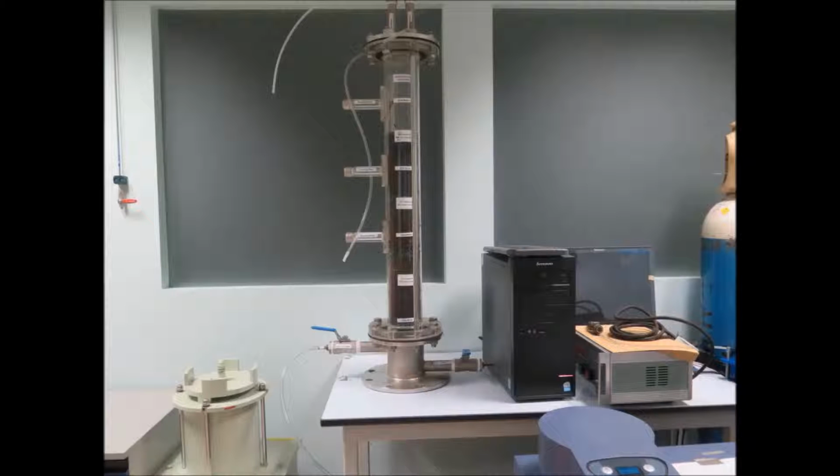So you basically increase the absorptive capacity. Exactly. We do the carbonization, at the same time we create porosity, using a chemical reagent at a particular temperature, and in the end we come up with a highly hydrophobic material with a very high surface area. We're talking about 2,500 square meters per gram, which is far higher than what you get typically from commercial activated carbon. On top of it, it's also hydrophobic and has high porosity. We're talking about microporous materials, less than 2 nanometers. So it's actually nanoporous. Exactly. It also has a lot of other innovative attributes which I can share with you if you have time.